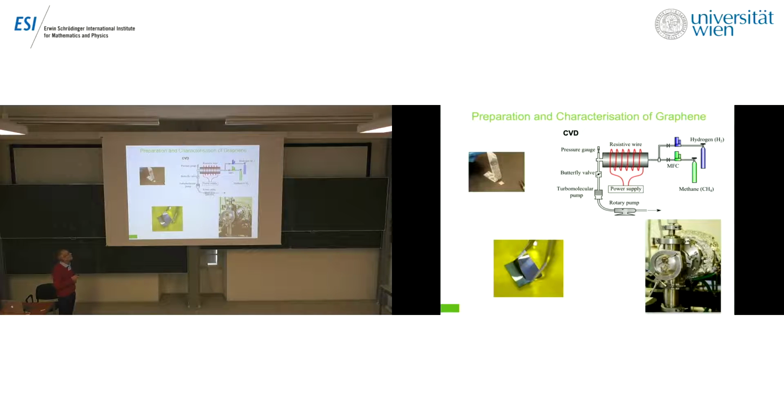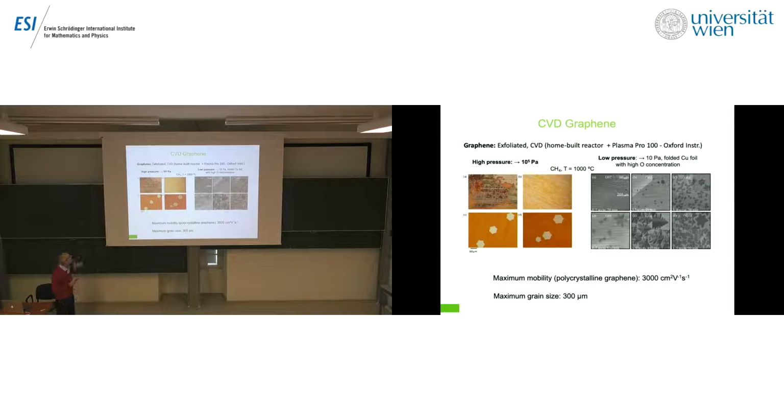So, one of the major, most spread and popular methods is CVD, chemical vapor deposition, where you have a reactor and you put inside some gas, so for instance methane, and then at high temperature you will decompose it using some metal catalyst, for instance copper. And this is the method exactly we do in our lab. Then after growing that graphene, you should somehow peel it off, or get it out of that metallic catalyst, the copper, so you do it by some chemical way, which brings some problems, but I will not go into detail. So in our lab, we use also exfoliated graphene, but for applications I will talk about,